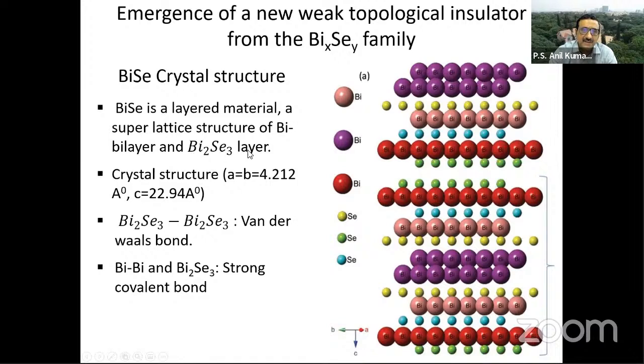So now let me tell you the structure of this weak topological insulator. We are all familiar with the Bi2Se3 topological insulator. Here we have two bilayers of Bi2Se3 and a bismuth bilayer. That means the structure is two Bi2Se3 layers coupled by a bismuth bilayer, so that the unit cell goes to around 23 angstroms. So Bi2Se3 plus Bi2Se3 plus two Bi forms the structure of this material. And this is a very interesting material.